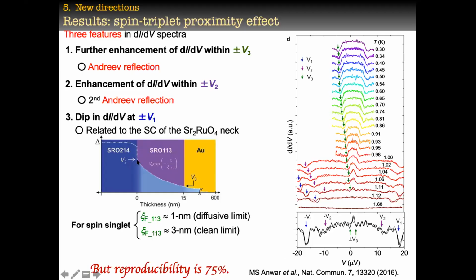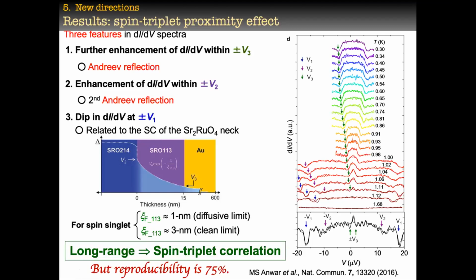So two Andreev reflections, meaning the induction of superconductivity is all over this ferromagnet. And all over this ferromagnet means 15 nanometers. In this ferromagnet, we can put spin singlet Cooper pairs, but only over a maximum of 3 nanometers, not more than that. It means that these Cooper pairs, those that are induced in this ferromagnet, are spin polarized. And a more important and encouraging thing here in these devices was that the reproducibility was more than 75%, with a very long life of these devices.